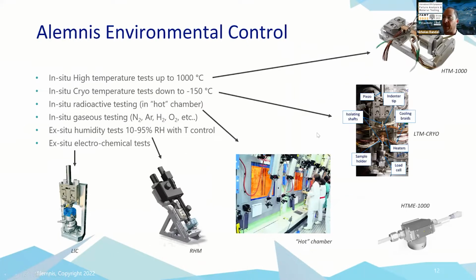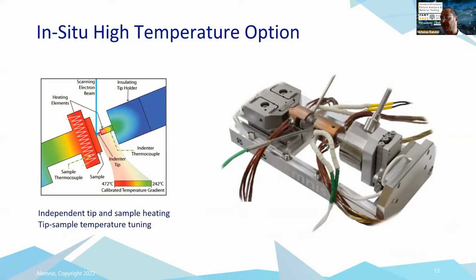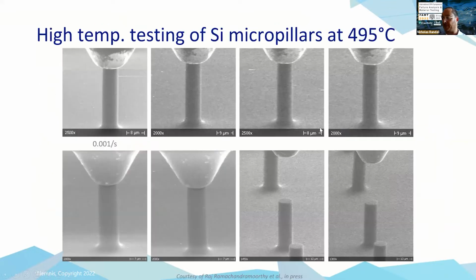So we can also couple that with environmental control. So we have, external to the SEM, liquid testing and humidity control. We can also do radioactive control and high and low temperature. So just to show you quickly a high temperature stage, here we're heating the sample and cooling it, and we're heating and cooling the indenter separately. And we bring them together so that we have a stable thermal contact. And just an example from semiconductor, here we have silicon micropillars being tested at 500 degrees C.